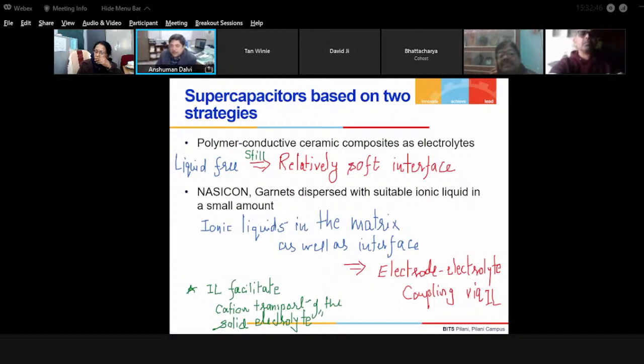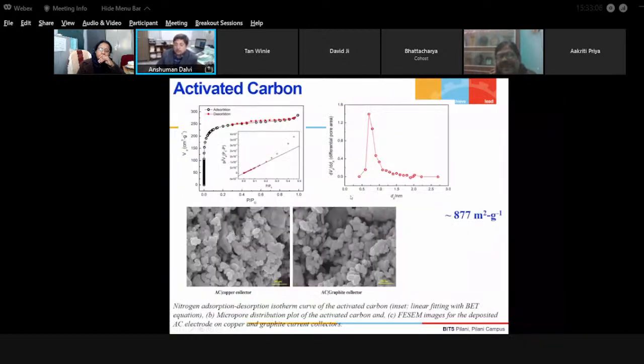Now this is the basic principle. But now we have a solid electrolyte, and how do we make a supercapacitor out of it? One process which I am discussing today is polymer conducting ceramic composites used as electrolyte. These electrolytes have to be pressed because the interface has to be smooth. For the type of Helmholtz layer expected, a good, highly activated carbon of about 800 to 1000 square meters per gram surface area is required. We can prepare this or get it from somewhere, and then the electrodes are ready.